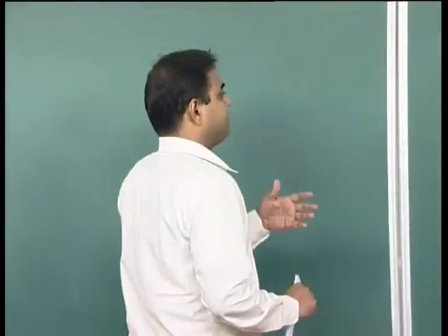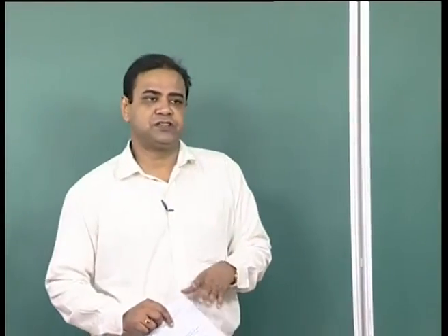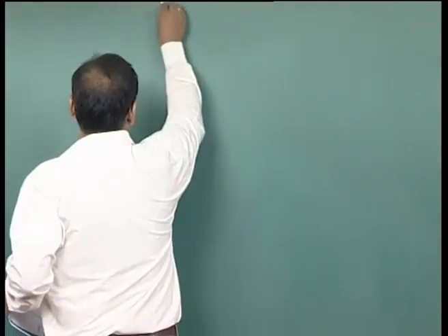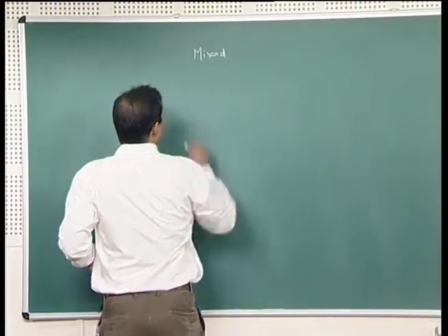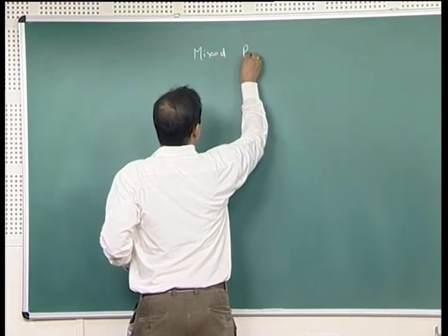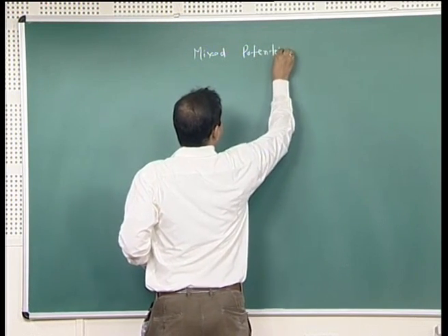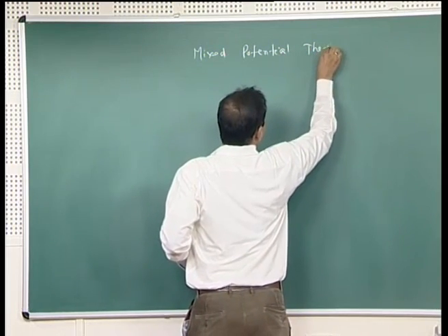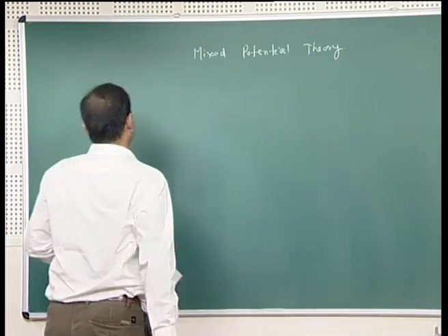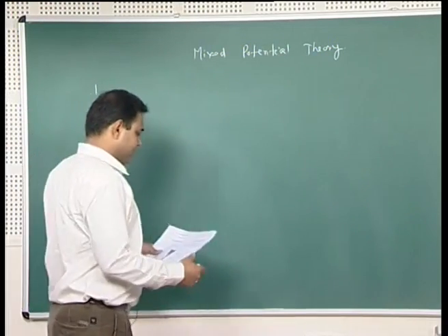But when you connect this iron and zinc together and put them in HCl solution, you will see that the corrosion rate of zinc is more than the corrosion rate of iron. All those corrosion observations can be easily understood from this mixed potential theory. And we have started mixed potential theory with two postulates or hypotheses.